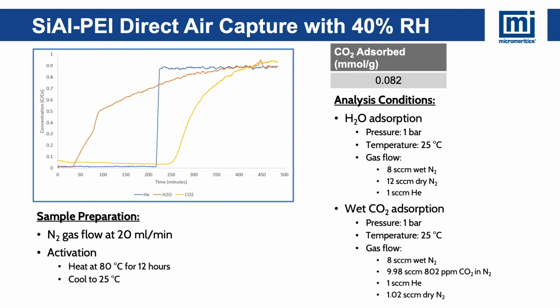Now, looking at it, once we add in water, what happens? Well, we actually see a pretty substantial drop in our capacity. So what we did here is we started by saturating our adsorbent, the silica alumina with PEI, with water by flowing water at 40% relative humidity for 3 hours. And then we started introducing our helium as well as our CO2. And we see roughly a 50% decrease in capacity, only reaching a total quantity of CO2 adsorbed of about 0.082 millimoles per gram.